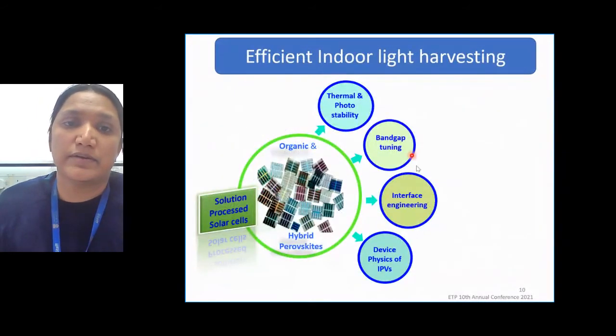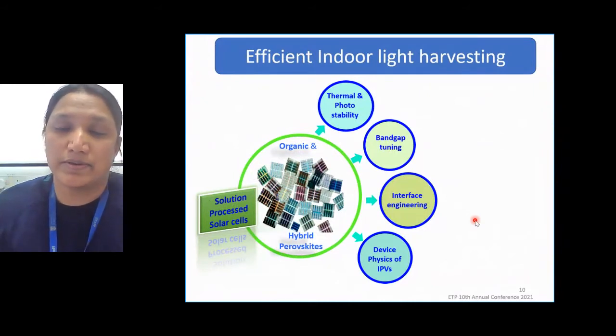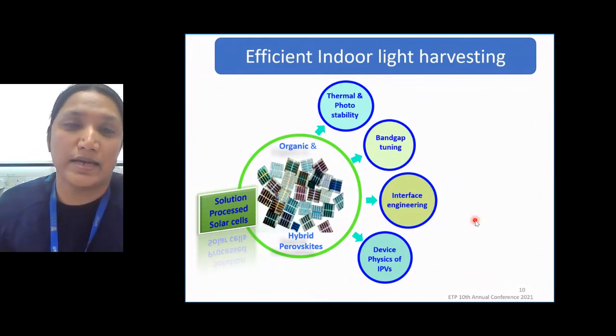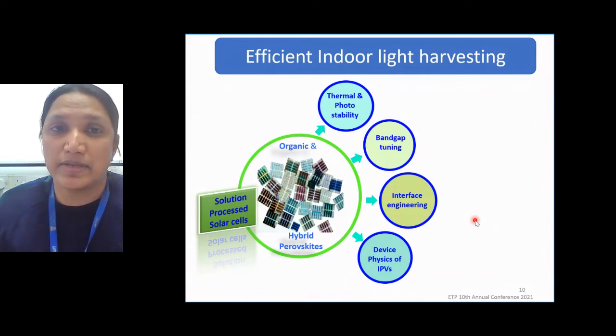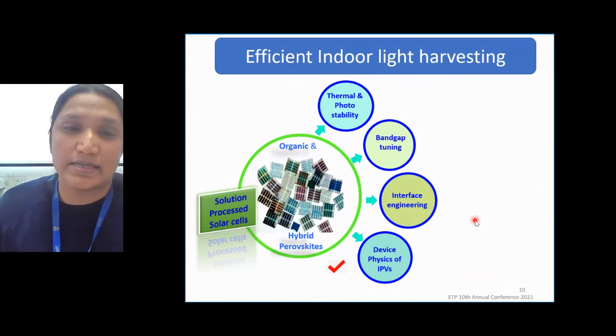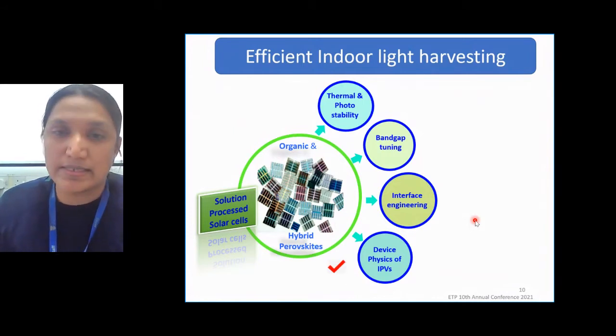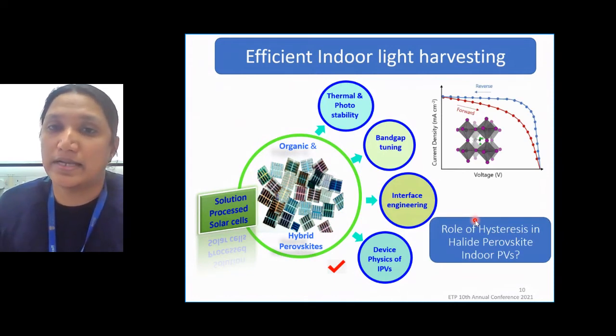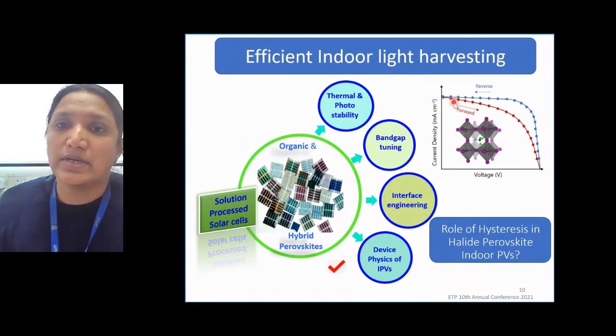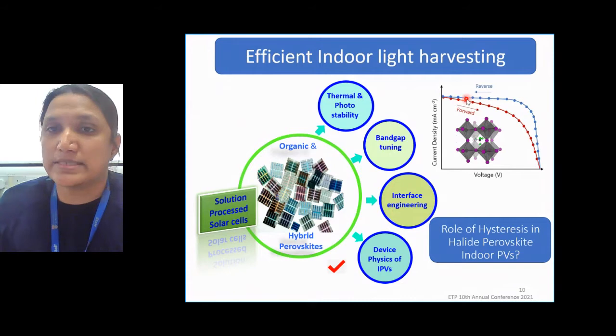So in our energy harvesting research group, one part of our research is focused on the indoor photovoltaics of these halide perovskites: how can we enhance their efficiency, how can we enhance their device stability, and also understanding their device physics. Today I will be talking about one such aspect, which is related to the hysteresis effect in halide perovskite photovoltaic devices. Hysteresis refers to the situation in which the JV curve follows a different shape or different directions depending upon the voltage scan, whether it is a forward scan or reverse voltage scan, and also depending upon the voltage range we apply and with what voltage step. It means that different shapes will show different power conversion efficiency values depending upon the voltage step or the voltage scan range.